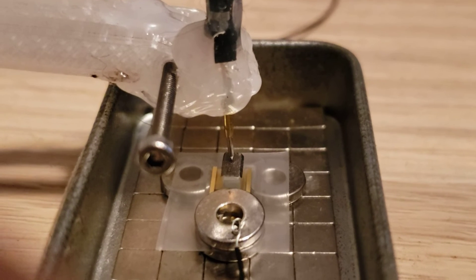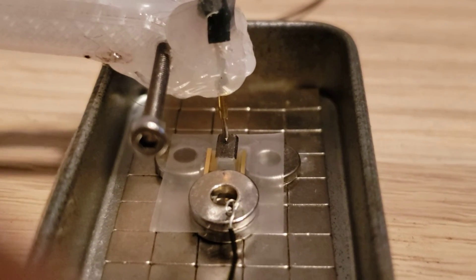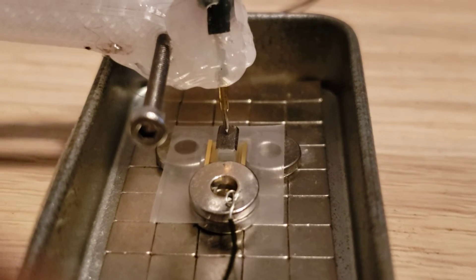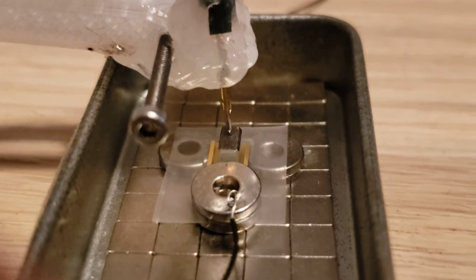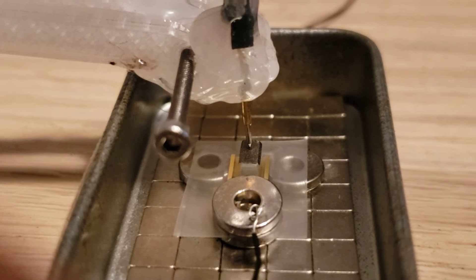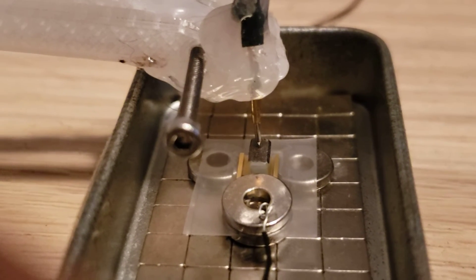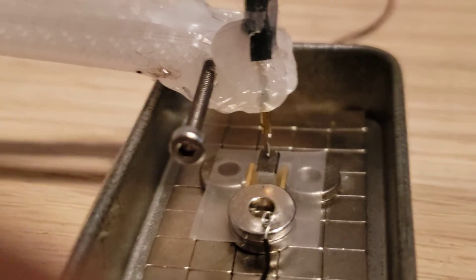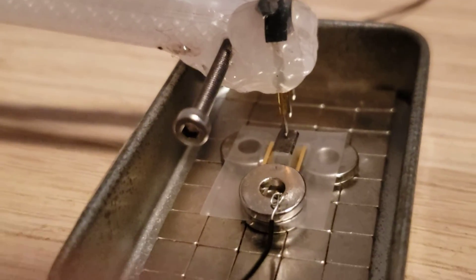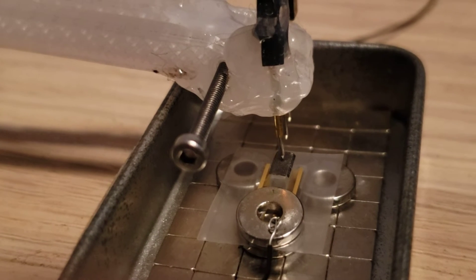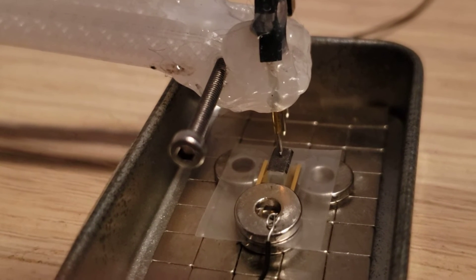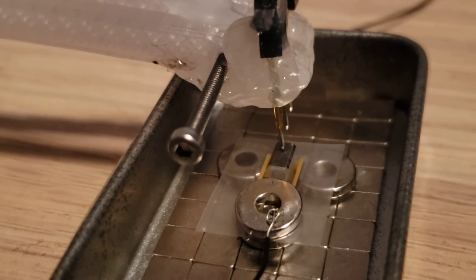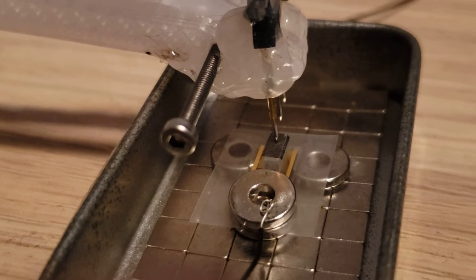So it can be done with more or less bespoke components. I'm actually using an off-the-shelf neon sign power supply, a high-voltage transformer, which can create an effective field of around 4 kilovolt total, so 2 kilovolt per millimeter, because this crystal's orientation is roughly 2 millimeters in thickness, 5 millimeters in length, and this can hopefully induce periodic poling on this crystal.